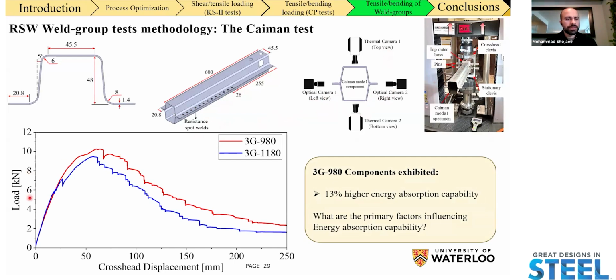I've summarized the load displacement response of the two tests. What we essentially see is a discrepancy in terms of the peak load and the energy absorption capability. Specifically, the 3G 980 is showing us superior performance. And what we really want to know is why this is happening. What are the major factors that are influencing the energy absorption capability between these two materials?